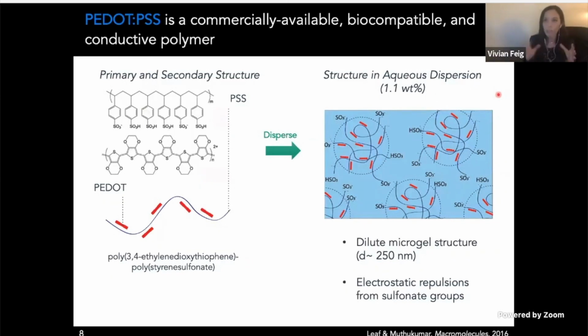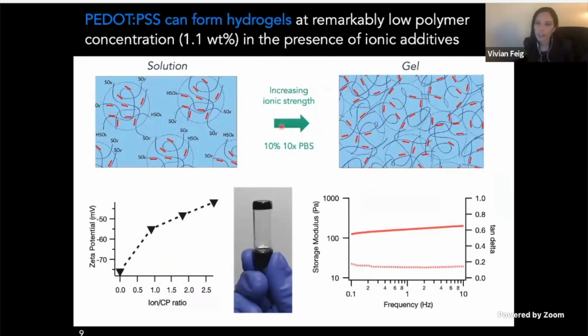And if we look at what this looks like in solution, the PEDOT:PSS forms these dilute microgel particles whose primary interparticle interaction is electrostatic in nature and really driven by these repulsive forces between negatively charged sulfonate groups on the PSS. And so that's why the microgel particles can flow past one another and behave as a viscous liquid. When you increase the ionic strength of these solutions, you can screen those electrostatic repulsions and actually get the PEDOT:PSS microgels to aggregate into a physical hydrogel.